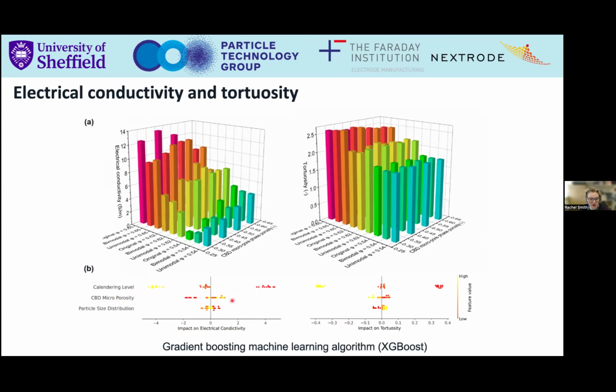The microporosity had quite a substantial effect on our conductivity, and interestingly, the particle size distribution didn't have a huge effect. Now we know that the active particles don't participate too much in the conductivity, and it's much more the conductive particles that are controlling that. But at the same time, I was a little surprised to see such a small effect of the particle size distribution because of the effect of that on the pores in the electrode. And similarly, we can then look at that impact on tortuosity. And in this case, we're using tortuosity as a way to think about the ion transport within the electrode.